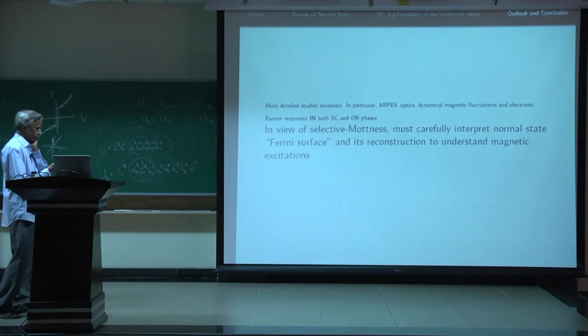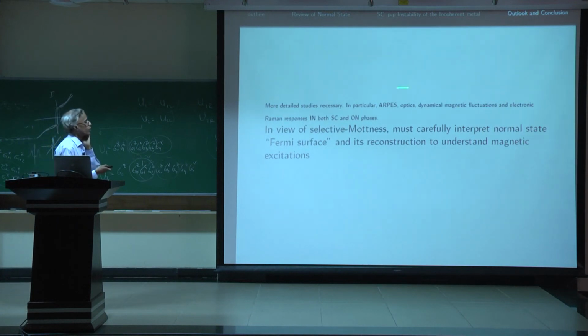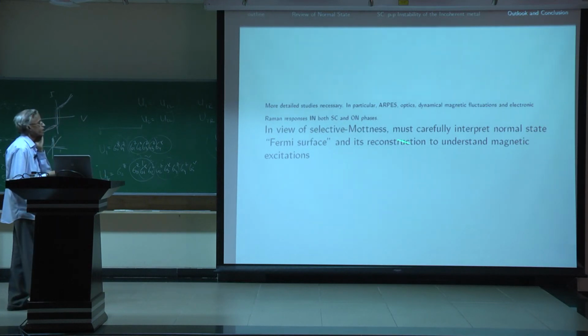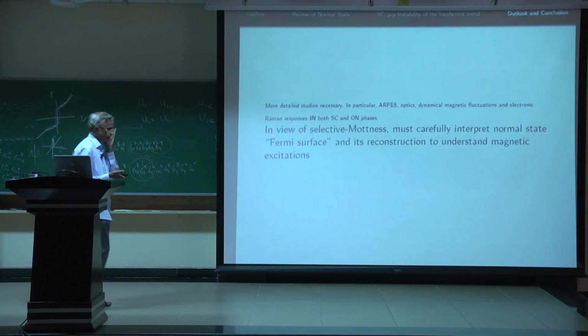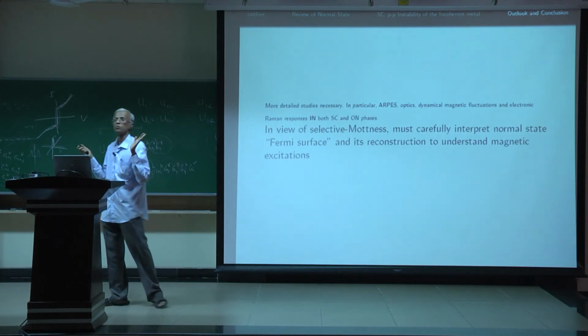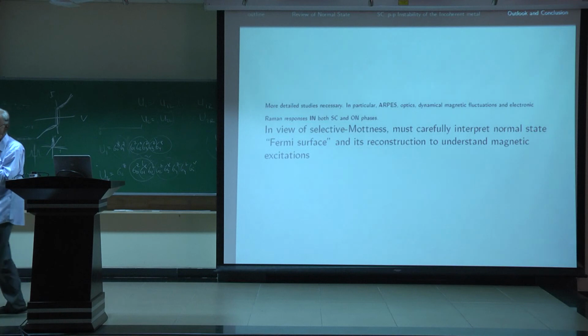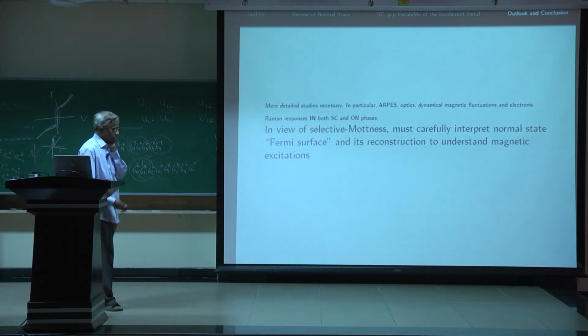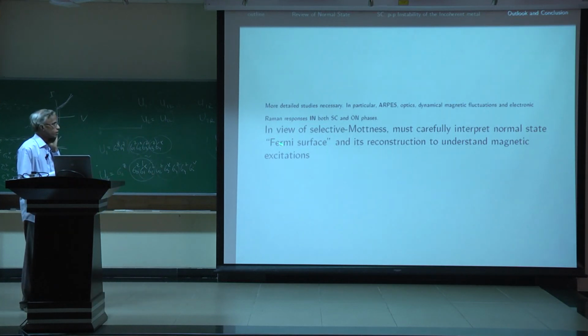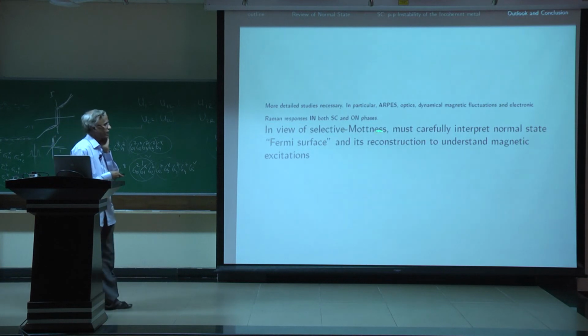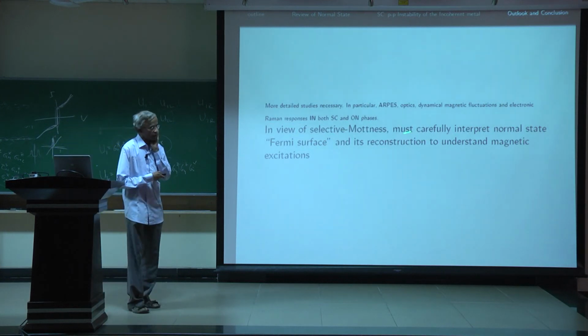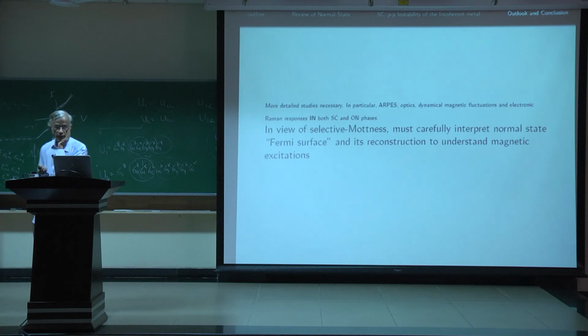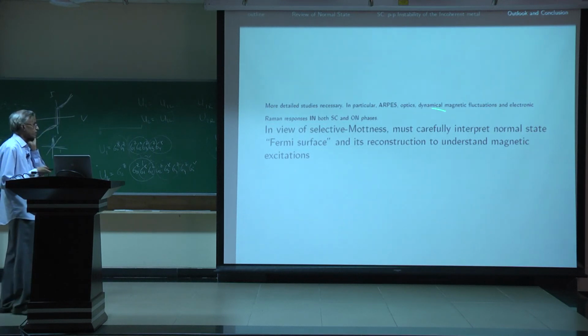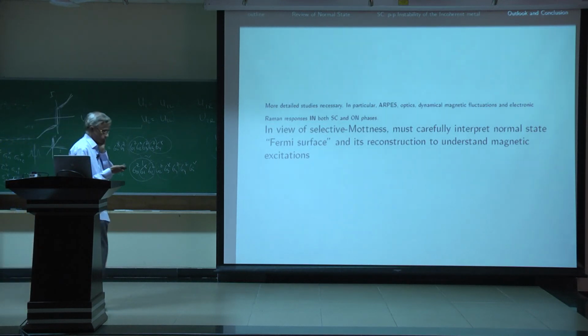Okay, so what this tells, among other things, is basically that in view of selective Mottness, which implies that the Luttinger surface, which encloses the total number of electrons, is associated with the zeros of the Green function rather than the poles as in Fermi liquid theory, the whole idea of Fermi surfaces and its nesting properties that is invoked in description of antiferromagnetism in itinerant pictures may need a reinterpretation. Okay.